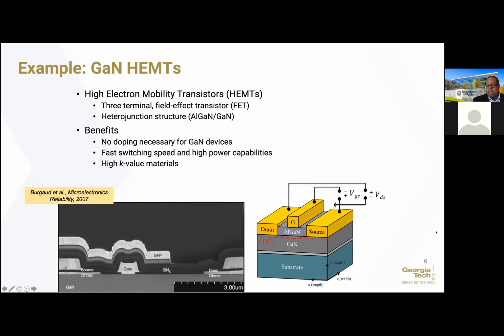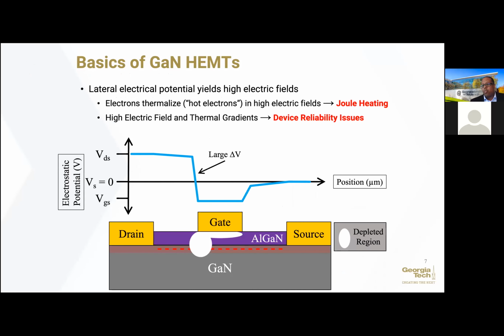But as I said before, due to the lack of large numbers of native substrates, you typically have to grow this material on top of another substrate. That's going to introduce some challenges when we look at power dissipation. So where does the power come from? When we're flowing current through this two-dimensional electron gas, I can pinch off this gate, which depletes my channel, so I don't have carriers in the channel. And as I manipulate the negative voltage on this gate, I can begin drawing electrons or carriers into the channel, which causes the current to flow.